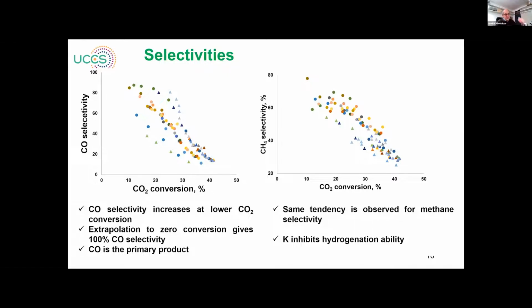When we have CO2 hydrogenation on iron catalyst, CO2 is first hydrogenated to CO. Then we see the same thing for methane. For methane, this is actually selectivity to methane without considering CO production. So we see that methane also decreases with conversion. So if we go to 0, we reach maybe 70, 80%. And we also see that if we use a catalyst promoted with potassium, the production of methane decreases compared to the same catalyst which doesn't contain potassium.